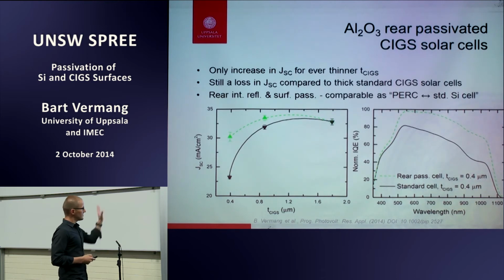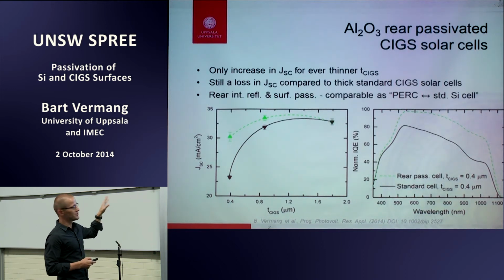JSC, same thing. JSC as a function of CIGS thickness for a passivated one in green and an unpassivated one in black. And you see you have more JSC if you have the rear passivation layer. However, you still lose some if you compare to the thick cells.